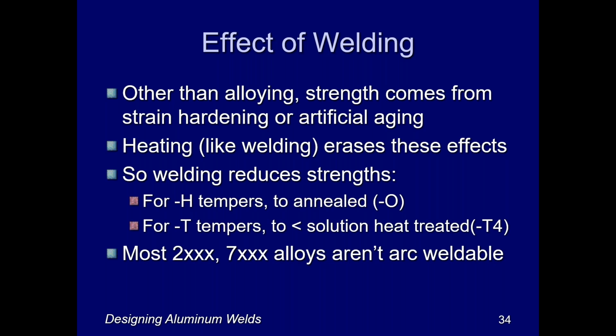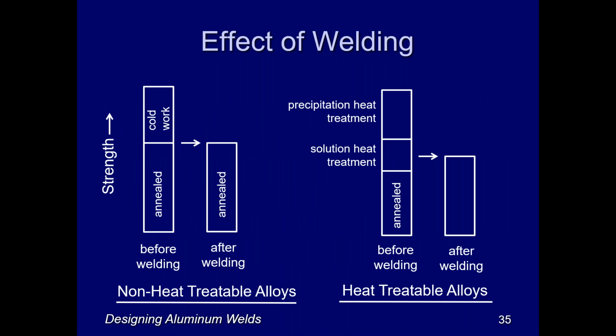So for H-temper material, welding reduces the strength to the annealed condition. And for T-tempers, it reduces the strength to something a little bit less than the solution heat treated, or T4 condition. And then keep in mind that some alloys are not arc weldable. Those would be typically in the 2000 and 7000 series. So to kind of show this graphically, to maybe make it a little bit clearer, there's the non-heat treatables and the heat treatables, and they respond a little bit differently. But most extrusions tend to be heat treatables, say 6063, T5, T6.